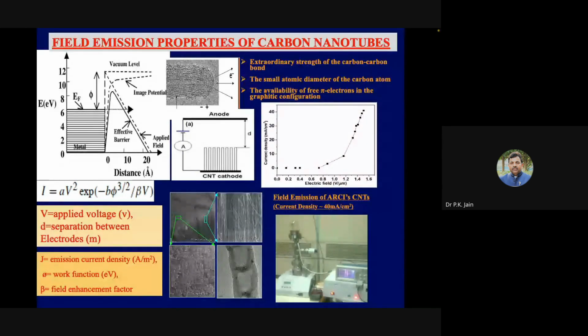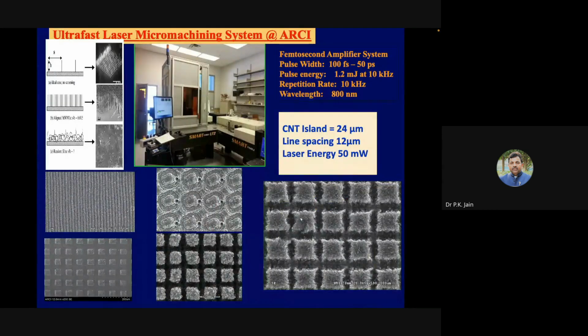These carbon nanotubes were developed for defense applications, and we have observed that the highest field emission is possible from the edges only. So when you develop a film into a plate, we found that if we can incorporate more edges, then the field emission can be increased.